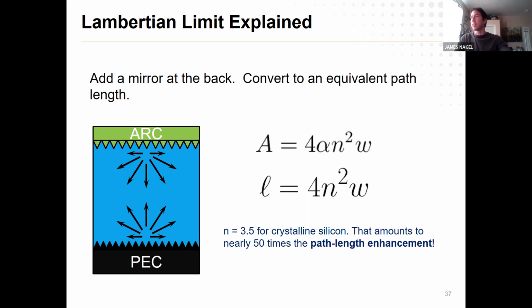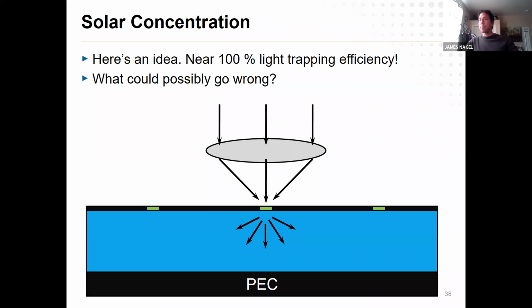So for crystalline silicon, which has an index of refraction of about 3.5-ish, you square it and multiply by 4, and you find that you can get a path length enhancement of about 50 times. So a 1 micron slab of silicon, if treated correctly, can behave as if it is 50 microns thick. That's how you kind of describe the benefits here.